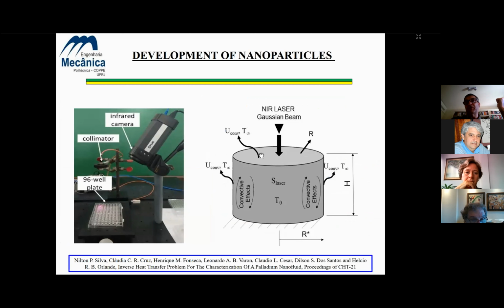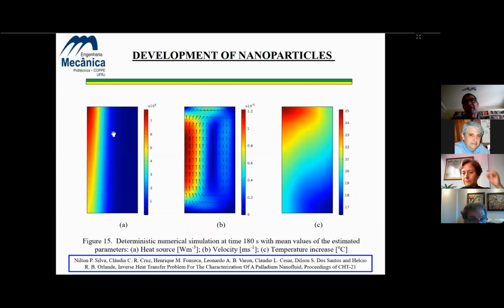in a natural convection model that considers the laser beam, and this is the nanofluid inside the well where convective effects take place. This is a direct simulation where we can see the heat source located along the axis of the well, where the laser is located, and the non-uniform heating induces natural convection currents, and actually results in very different temperatures inside the well. You see, this is the temperature increase, where it's here around 25 centigrade. At the bottom it is around 17 centigrade.